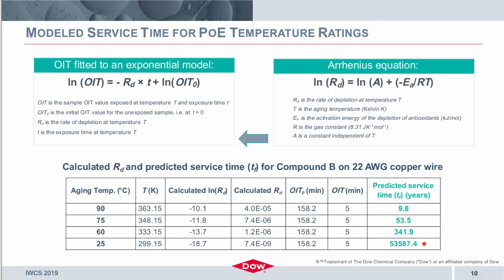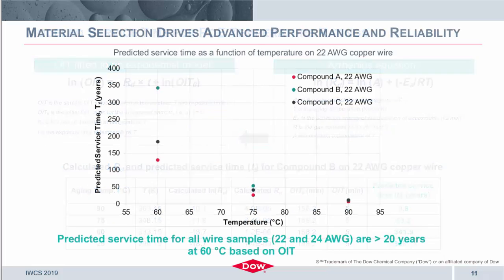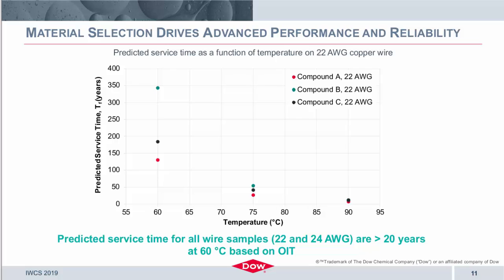As you can see, if you plug it in and kind of in between 60 and 25 degrees Celsius, which would be more or less room temperature, you're over 50,000 years of service time when you look at something at the lower temperatures. But nonetheless, as I mentioned, very high predicted service times for the given temperatures typically considered today. So really, that just shows you how we built the model and gave you the example of one of the materials.